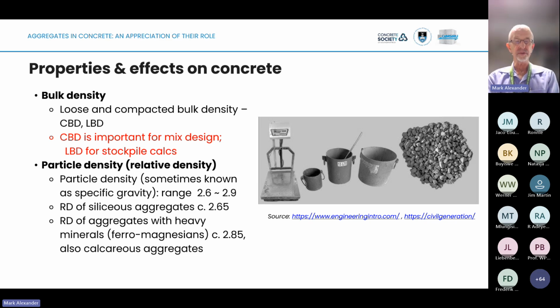Then particle density, the density of the actual aggregate particle itself, sometimes known as specific gravity. And here, these are rock materials, so they're going to fall in that range, roughly 2.5 to 3. Siliceous aggregates, generally about 2.65. And then the ferromagnesians, those would be the dolerites and those kinds of things. They have some heavy minerals in them, so the density goes up a bit. Also calcareous aggregates. And we need to take this into account. It will affect our mix proportions and how much of this material we can put into the mix. So that's a very important number, and we use it extensively in concrete technology.